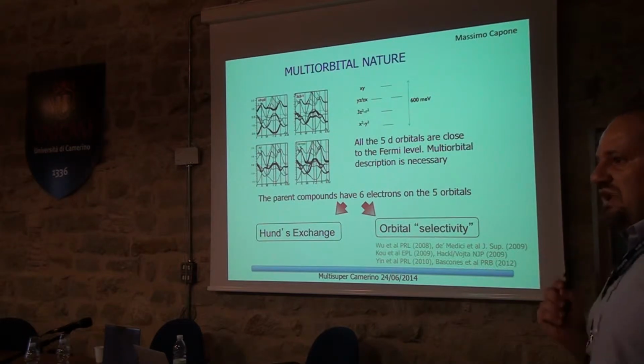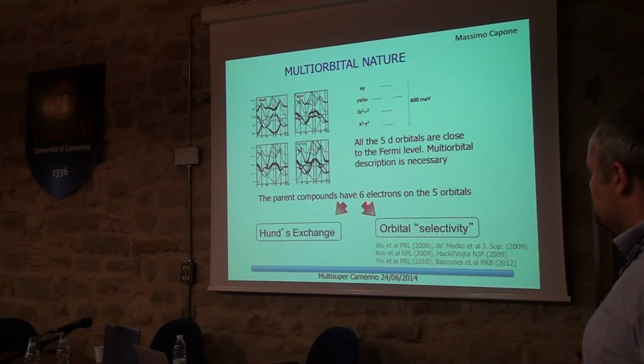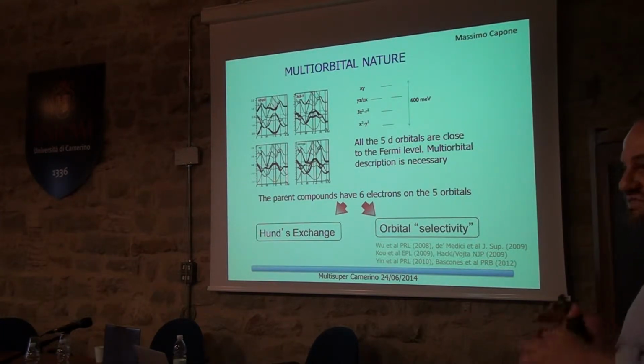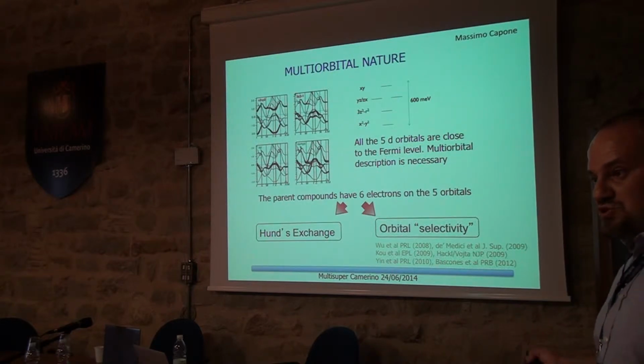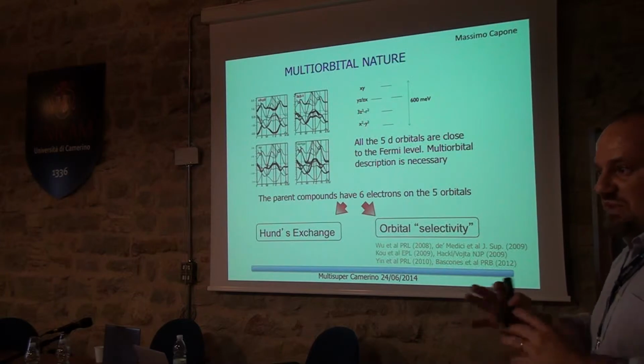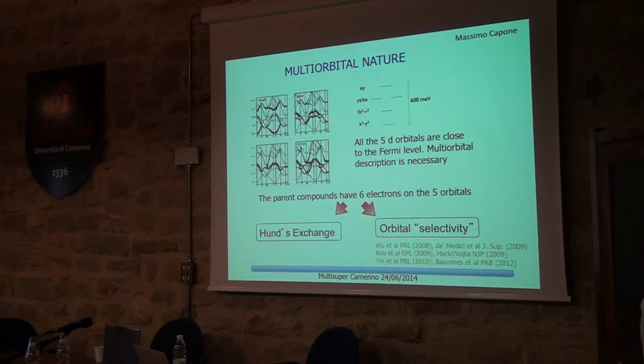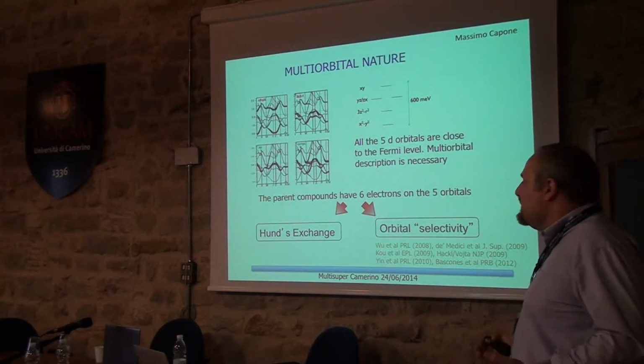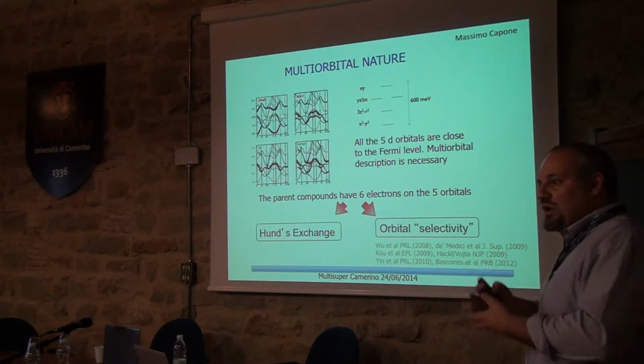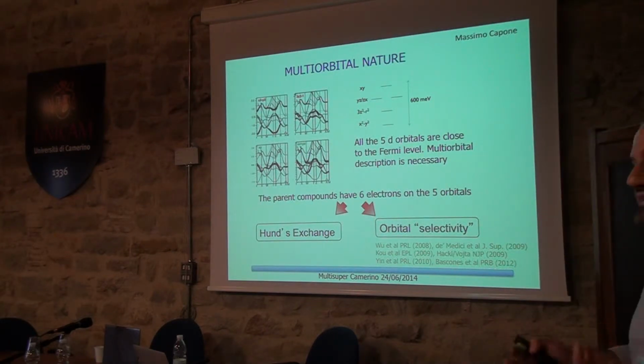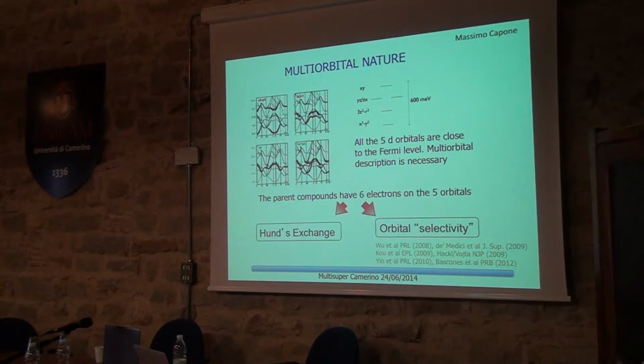Let me mention that the count of the electrons in these materials would be, if you take a fully pure description in terms of iron d orbitals, 6 electrons on the 5 orbitals of iron. So it's an integer number, but it's not half-filling. It's not the same number of electrons as the number of orbitals. This brings about at least 2 important effects. One is the role of the Hund's exchange. If I want to build some theoretical description of what happens, I have a multi-orbital model. If I am reasonably close to some atomic physics, the local Hund's exchange will play a role. And the other is that there is at least the chance that the orbitals will behave differently from one another, which is what I call here orbital selectivity. So the behavior is not the same for all the orbitals, something that Sergei once again was hinting at some point during his talk.